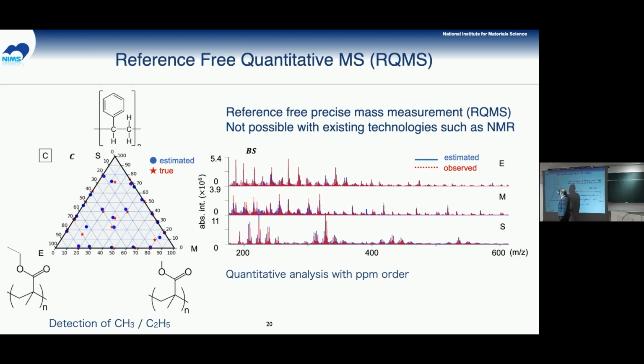There are several surprising things to us. One is that in these cases we don't need the reference data. All you need is just a mixture of these components. Then we can estimate the zero point. That is very important: you don't need pure reference samples. Also, only the subtle change between the methyl group and the ethyl group can be identified, which is quite difficult by NMR, methyl versus ethyl.